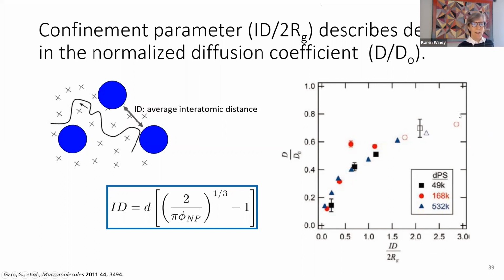And, you know, we didn't redo that data point. And the error bars are from duplicate experiments. And so this is really remarkable collapse for a challenging experiment. And so the magnitude of the decrease is almost an order of magnitude when we have a very small ID over 2RG. And when we're at an ID over 2RG of 3, we're still 25% below, or nearly 30% below the bulk diffusion coefficient that's expected. So very much princess and the pea.